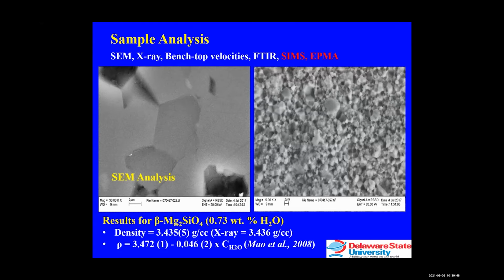We conduct X-ray analysis to confirm the sample is single phase. We measure the bulk density and compare it with the X-ray density, and also measure the water content in the case of the hydrated sample, which is something I'll talk about later. So these are scanning electron microscopy analyses of the polished and cracked surface of wadsleyite containing 0.73 weight% water, which we already published. The scale bar is 1 micron on the polished surface and 2 microns on the cracked surface. As seen here, there is no observable porosity at the triple junctions of the polished sample. The average grain size estimated from the cracked surface is 5 microns, and the orientation of the grains is